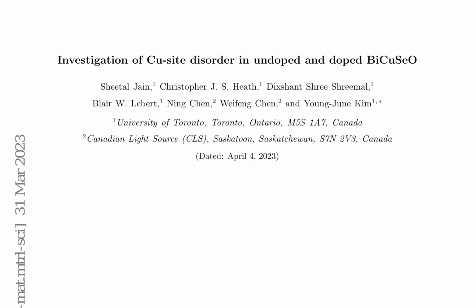Extended X-ray absorption fine structure, EXAFS, measurements were conducted at the Canadian Light Source, CLS, on the hard X-ray microanalysis, HXMA, beamline 06ID-1 to investigate the local atomic structure of doped and undoped BiCuSeO samples. Room temperature, 298 K, measurements were performed for Ag K-edge, 25,514 eV, and Cu K-edge, 8,979 electron volts. Data collection.